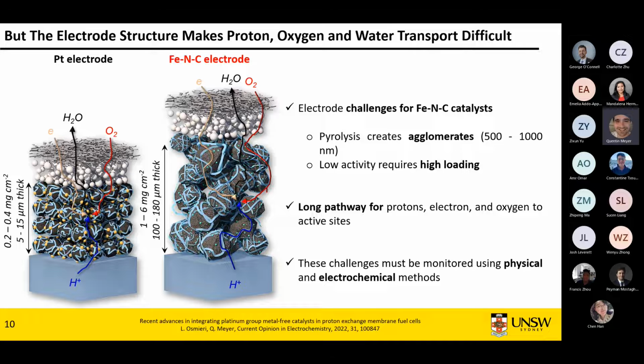What you get is a very thin electrode, 0.2 to 0.4 milligrams per square centimeter, and in terms of thickness, 5 to 15 microns. You've got some very nicely distributed platinum particles on small carbon nanoparticles, and you've got a very nice interaction between your ionomer and your particles. That's pretty good. Now you look at PGM-free catalysts, a much more recent material. The ink is not optimized yet, and there is still a huge amount of work to do in this area. The kinds of problems you have, let me play this one,